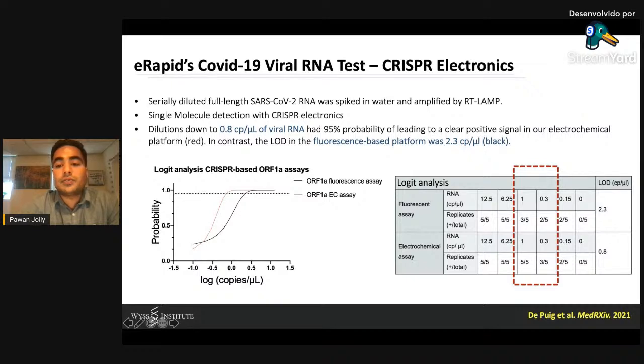You can see the fluorescent assay at 1 copy was able to differentiate 3 out of 5, while the electrochemical was able to differentiate all 5 out of 5. So when you plot this, we were able to get a sensitivity of 0.8 copies per microliter with our electrochemical sensors, which is literally looking into atomolar detection.